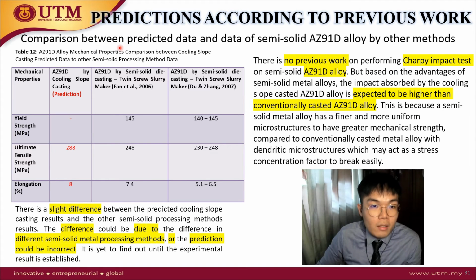And then we compare the predicted data to other data of semi-solid AZ91D magnesium alloy. So this is not produced by cooling slope casting, but with other semi-solid processing methods. So you can see there's a slight difference between the predicted data, and the difference could be due to the different semi-solid processing methods, or the prediction could be incorrect, and it is yet to find out until the experimental results are established.